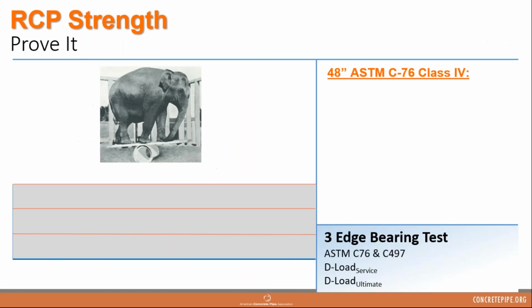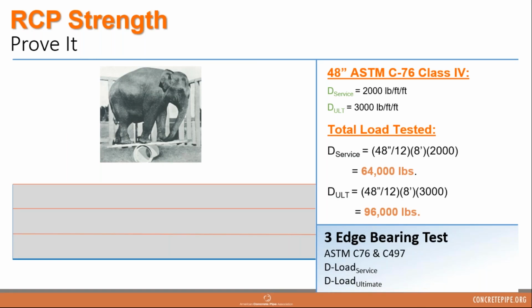So now let's look at how we come to these strength values. Still talking about that 48-inch Class IV pipe, we would take our D-service load of 2,000 pounds per foot per foot and the D-ultimate load of 3,000 pounds, and we convert those D-loads as they are applied to this pipe. With the service load, we convert 48 inches to feet, so 48 divided by 12, multiply that by an 8-foot length, which is our standard pipe length, and then multiply that by the service load of 2,000 pounds per foot per foot. If you follow all those units and multiply that out, that gives us 64,000 pounds.